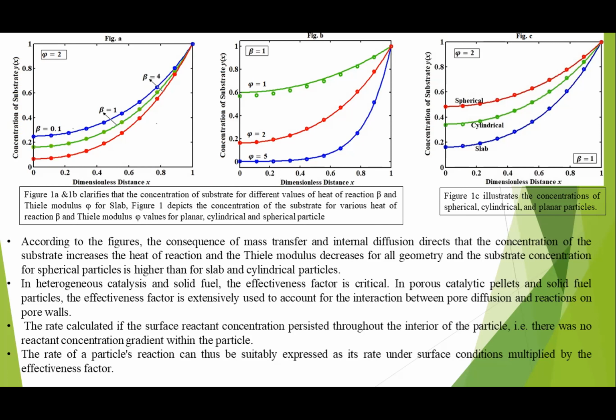The first two figures clarify the concentration of the substrate for different values of the heat of reaction. Figure 1 specifically depicts the concentration of the substrate for various heat of reaction beta and Thiele modulus phi. The values for planar, cylindrical, and spherical particles are given separately. According to these figures, we found that the consequence of mass transfer and internal diffusion is that the concentration of the substrate increases as the heat of reaction and the Thiele modulus decrease for all geometries, and the substrate concentration for spherical particles is higher than for slab and cylindrical particles.